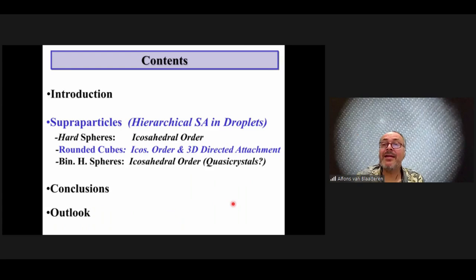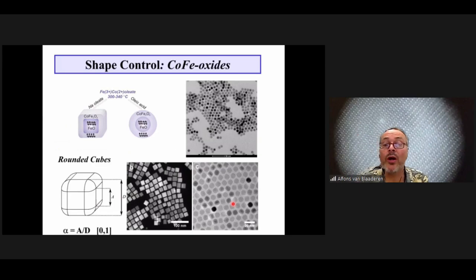So what now happens if we make the spherical shape slightly different? The iron oxide nanocrystals that I talked to you about before can actually, by symmetry, and I'm not going to go into the details of that, be turned all the way from a single crystalline spherical particle to a sharp cube particle. It's not 100% sharp and cubed, because there is also a ligand layer around it. So it turned out that even this ligand layer of 1.5 nanometers thickness was important to explain the self-assembly behavior that we saw.